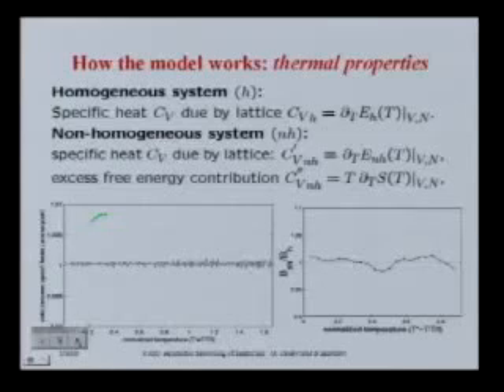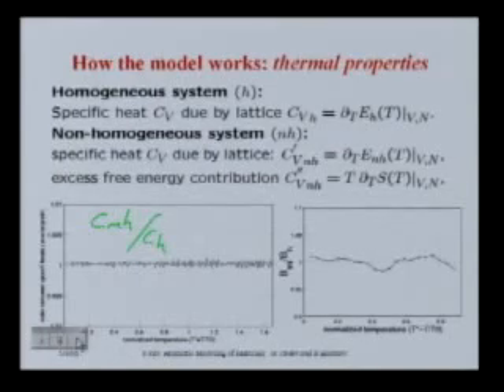If you keep track of the entropy right, you'll get things like the heat capacities right. This is the ratio between the heat capacity in the non-homogeneous system, which is the coarse-grain system, divided by the exact result—the heat capacity in the homogeneous system. It essentially oscillates around 1 as a function of temperature. So by construction, you pretty much have that right.